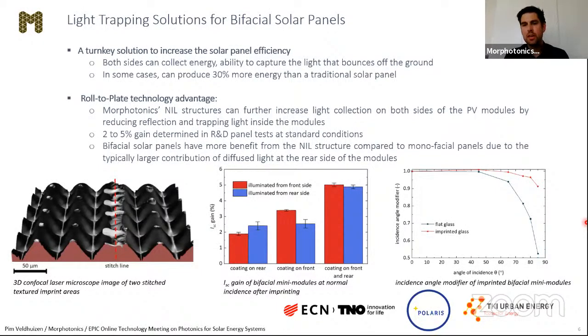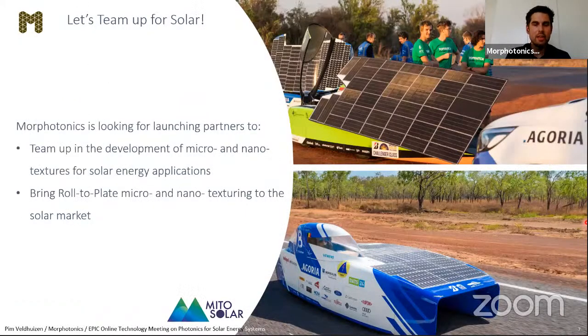And here, a second benefit from our texture comes into play. You can see that on the right graph, the incident angle modifier. This shows that the imprinted glass is more efficient in transmitting or capturing light that is under a large angle. So these two benefits come together in the field, and they will really enhance the efficiency of the module. This is currently being tested in a test location. So this is one of the applications that we have developed.